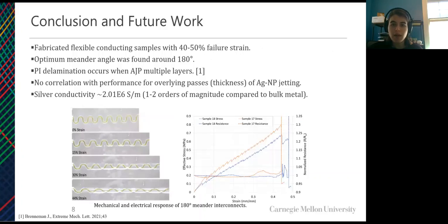In conclusion, aerosol jet printed stretchable interconnects are demonstrated with multi-material construction with a maximum failure strain of 44% for the 180 meander angle design, and images during the stretch and the corresponding mechanical and electrical data are presented here on this slide. High temperature processing of up to 300 degrees Celsius is demonstrated in an additive manufacturing process flow compatible with solder reflow temperatures.